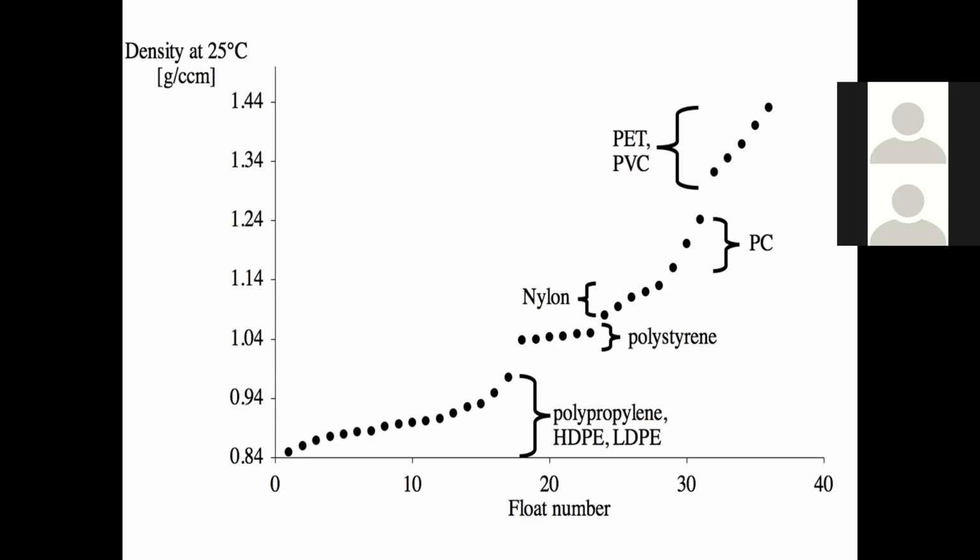After drawing the straight line, you know the height of your sample. So suppose the height of your sample is 32. At 32, you will keep the point here and then draw a perpendicular line at that point. This line will cut the gradient line at a particular point. Where it cuts, that will be the density of your sample. In this way, we measure the density of different samples.